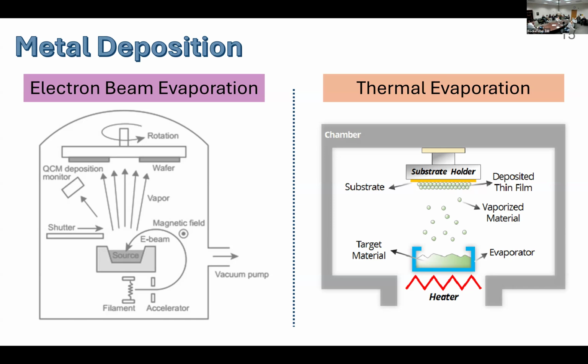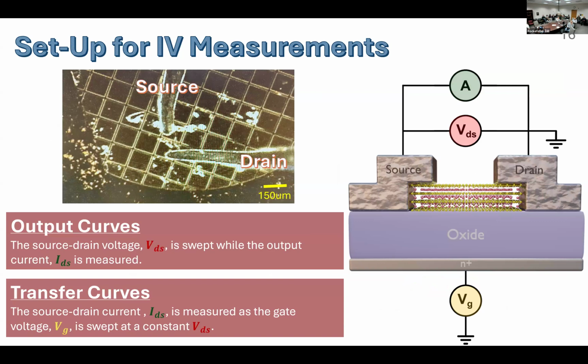After this, we finally have our device as pictured here. And we can go ahead and set up for electronic measurements. So using a probe station, we can probe the transfer properties of our device by taking current voltage measurements to generate two types of graphs. The first one being output curves, in which we're looking at how the source drain current changes as a function of the source drain voltage. And then we can also extract transfer curves, in which we look at how the source drain current changes as a function of the gate voltage for a fixed source drain voltage.